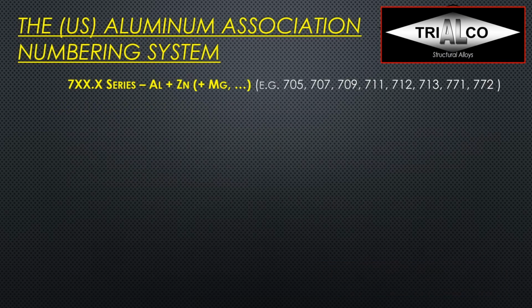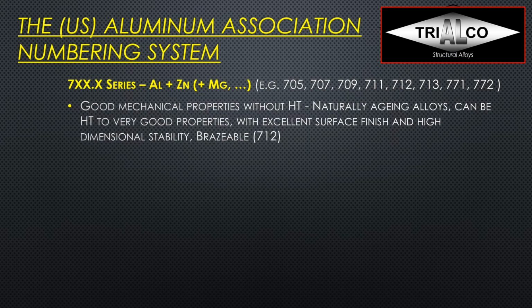Now the 700 series alloys, that is the aluminum zinc family that might also contain magnesium. Typical representatives are 705, 707, 711, 712, and 713, as well as 771 and 772. They all have very good mechanical properties without any heat treatment, so that's why many people also refer to them as the naturally aging alloys. But they can be heat treated to actually very good mechanical properties. They have excellent surface finish and high dimensional stability. And we have the 712 alloy in here that is also brazeable.